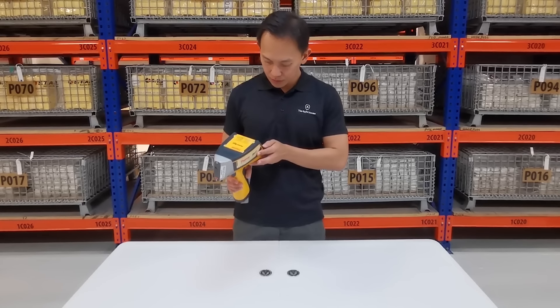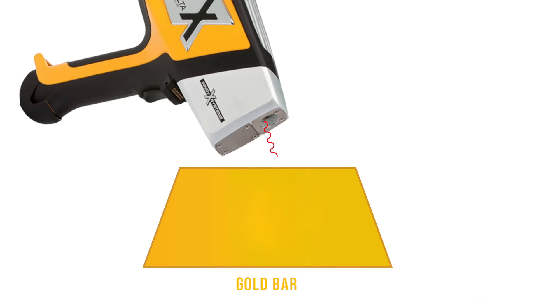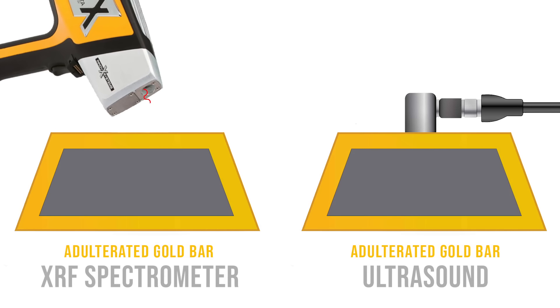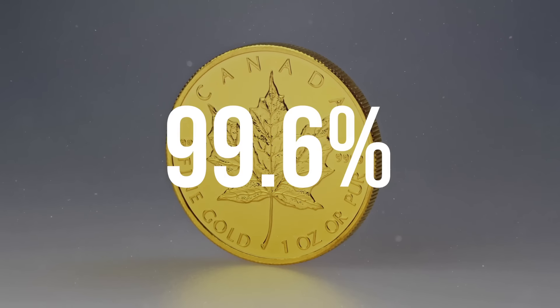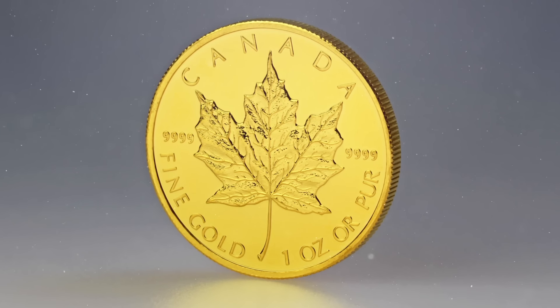X-ray. The composition of bullion can also be determined using an X-ray fluorescence, or XRF, spectrometer. It uses X-rays to quickly and reliably identify the metals present on a sample surface and provide purity readings. However, X-ray fluorescence tests are only surface tests, as they bounce off the surface without penetrating into the tested material. Therefore, unlike an ultrasound test which can detect counterfeit bars having only a gold surface layer, an XRF test may give an incorrect result as it is unable to detect what is inside the bar. Foreign material deposited on the tested surface can also affect accuracy. For example, a gold maple leaf coin of 99.99% purity may show a 99.6% reading if scratches or other factors left foreign deposits on the coin surface, even though there is nothing wrong with the gold inside.